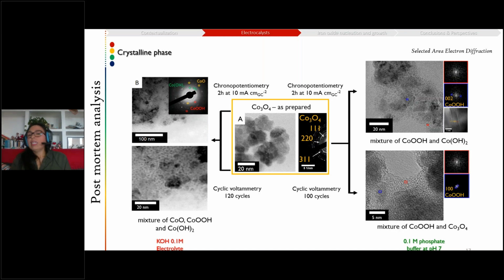But if we do cyclic voltammetry, we don't find the small crystallites, but rather a very small layer of cobalt hydroxide and, in general, cobalt oxide, meaning that this reaction in this solution is probably more reversible than in the potassium hydroxide.